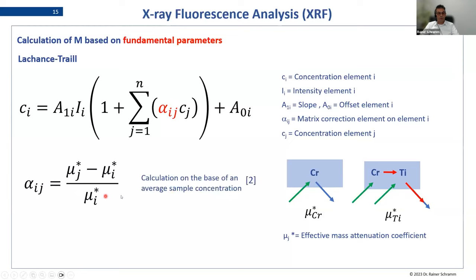Important, when we do it like this, we call this constant alpha correction. And we need to define a typical sample for that. That means the concentration is more or less the same for all samples. And this means also that the correction is only valid for this mean concentration sample, or the typical sample you have to specify for this model. In the moment you get different samples, which are getting far away from this one, then the model is not working so properly. But we call this theoretical correction with constant alpha.